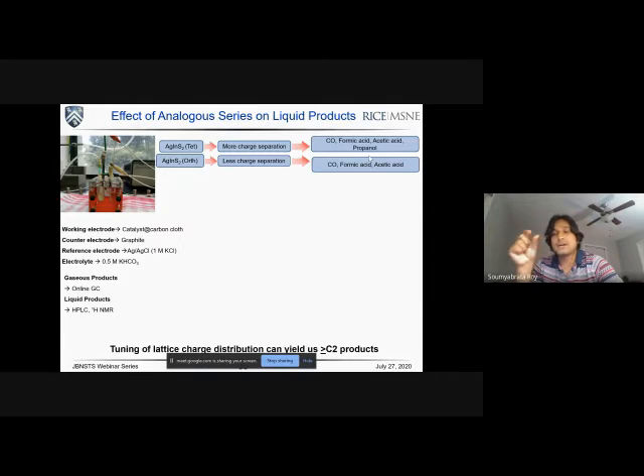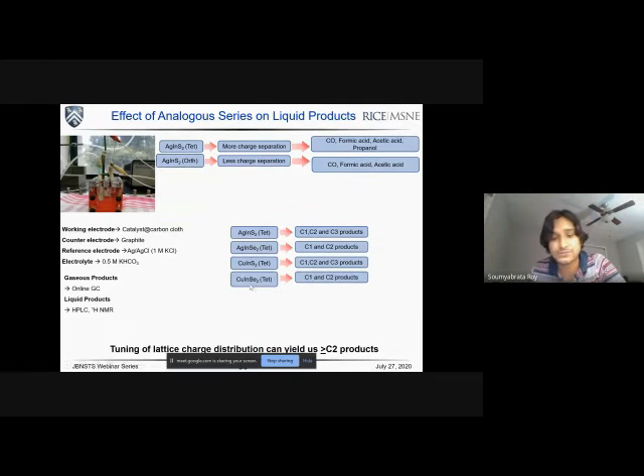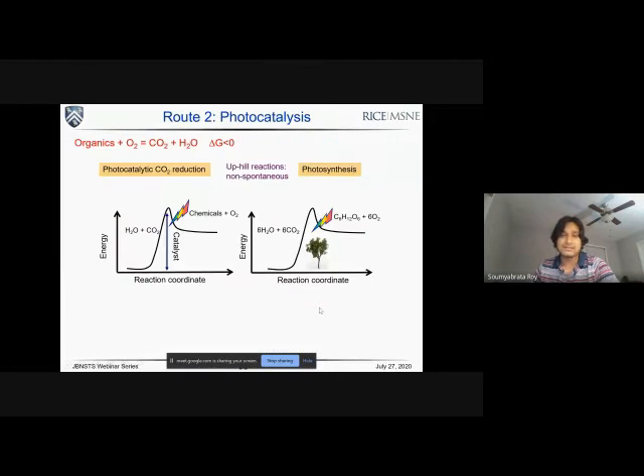So when you burn one molecule of propanol or one molecule of acetic acid, you will give different amounts of energy. So the higher the carbon, the more energy is stored in the chemical bond. So our target is to form higher carbon products. So we can see by a small molecular level modulation in the charge of atoms, how we can determine or change the course of product selectivity in CO2 reduction. So this is the key takeaway message: by tuning the lattice charge distribution, you can actually yield greater than C2 products, which is a very important discovery in this field.